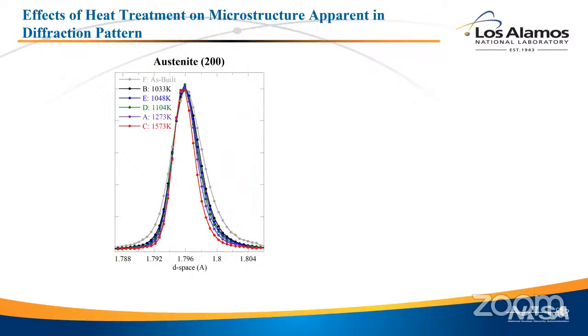For instance, these are our peaks. This is after it's said and done. From those 6 samples, F is as built. You see how broad F is. It's hard to see because it's gray. That being very broad is due to the dislocation density. You see C, which was heat treated to the highest temperature, is quite narrow. So the width of that peak is a look into the dislocation density.